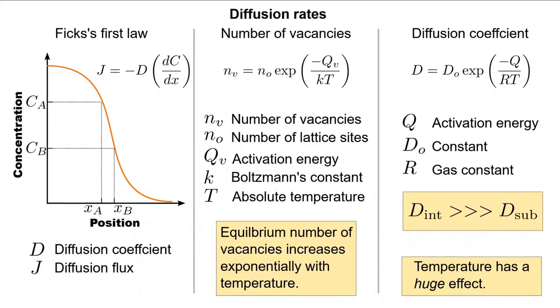For metallic crystals, the big picture here is that regardless of whether substitutional or interstitial transport needs to take place, there is a dramatically lower barrier to this form of transport as temperature increases. The increased numbers of vacancies diminish the overall activation energy for diffusion, such that the diffusion coefficient increases exponentially with temperature, in turn increasing the diffusive flux exponentially with temperature, even though Fick's first law is a linear relationship.